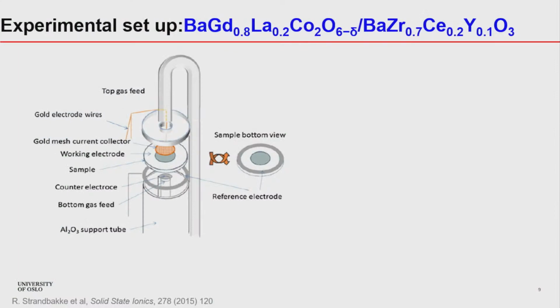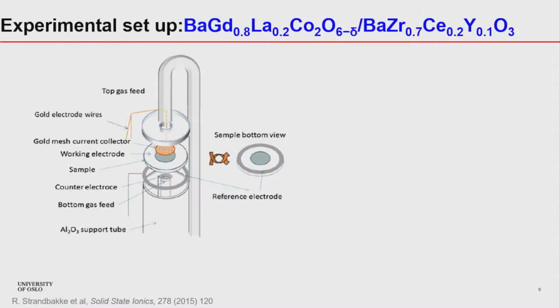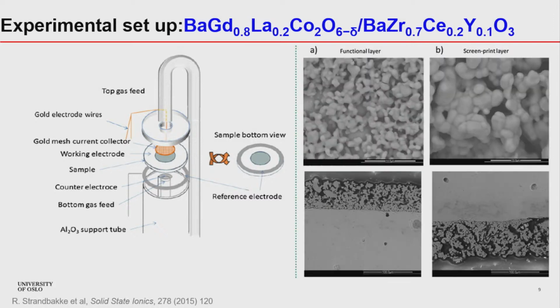As I said, we are going to study these materials as positrodes for the electrochemical cells. It is important to see how we want to study them. This is a typical diagram of a ProboStat from Truls Norby's company called NORECS. Here we can see that the sample is placed in between, and we have a working electrode on the top, the counter electrode at the bottom, and a ring to connect the reference electrode. This is the top view of the bottom side of the sample, where we have the reference electrode and counter electrode, and on the other side we have the working electrode. These are typical SEM images, which show what should be the case: a thick, dense electrolyte and a very porous working electrode in order to have proper gas transport.